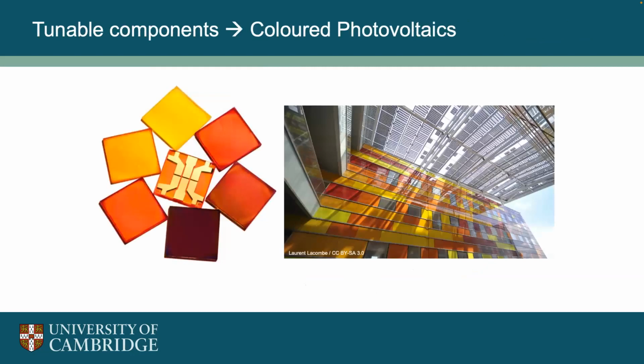The other thing we can do is tune the chemistry of these materials and actually tune properties like the band gap and tune the color of these absorbers. So this is an example where we are changing the halides from a pure iodide system and mixing in some bromides to move to a pure bromide system. And this opens up applications in building integrated photovoltaics. We can think about designing the PV cells into the building, rather than something that you put on the rooftop and try to hide, or put in a solar farm. So it's quite interesting, again, a paradigm shift.